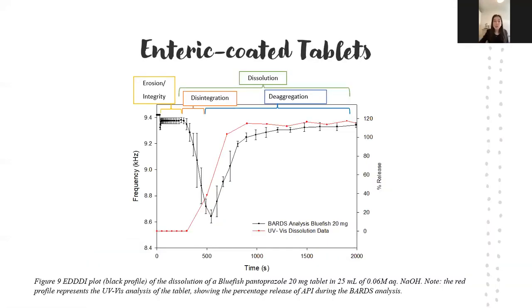And I'm going to present to you an EDDDI plot. So figure 9 shows an EDDDI plot for the Bluefish 20 milligram pantoprazole formulation dissolution. So BARDS is used to track the individual processes associated with dissolution. BARDS spectra of enteric-coated tablets and microspheres can be mapped using an erosion, disintegration, deaggregation, dissolution, and integrity plot. The red profile represents the UV-Vis analysis during the BARDS experiment. The UV-Vis profile measures the concentration of dissolved pantoprazole released from samples.